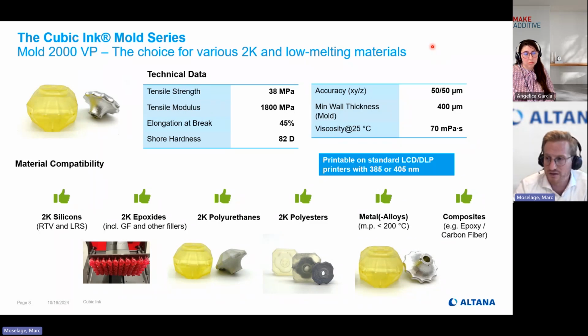The minimum wall thickness of the mold is 400 micrometers, which is very, very low. This is important, as it saves you a lot of money and time. If you have, for example, silicone to fill in, an RTV silicone, for example, is pretty low viscous, one could say, and easy to fill. So you do not need very big walls for that. It's just too much material, and you need more dissolution time. So 400 micrometers is something we can really print without problems.